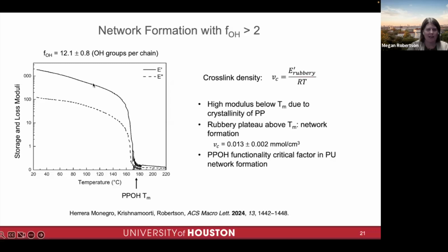And as we heat up, we go through a transition. This is actually very close to the melting point of the polypropylene, which we can measure through other methods. What you'll note is that at high temperatures, this does not continue to drop, but rather there's a plateau. That's telling us that we do indeed have a cross-linked polymer because it's acting like a soft solid at high temperatures rather than a viscoelastic liquid that you would expect if it were a linear polymer.